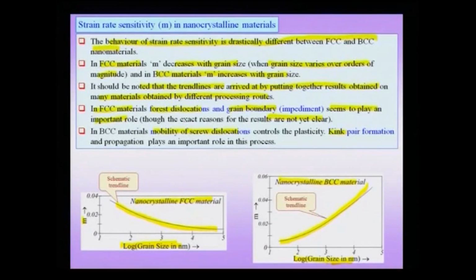And therefore, if I am doing a plastic deformation of a sample having edge and screw dislocations, or more precisely having edge and screw components, the edge components would actually leave the crystal, which implies that I will be left with more of screw components in the material. And this high Peierls stress implies that instead of the entire dislocation line moving, there is a mechanism, if you refer to the slide now, known as the kink pair formation mechanism. Its propagation seems to play a very important role.